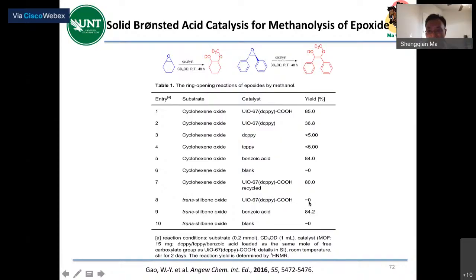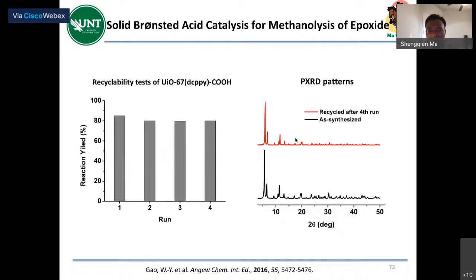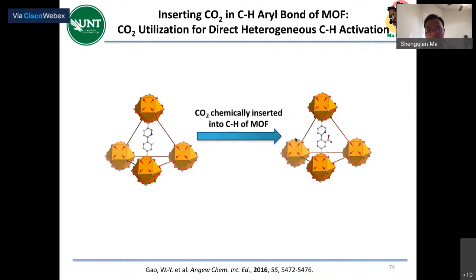There's no reaction, zero yield, because they cannot enter, because the window size of UiO is pretty small. The cavity is large, right? So we found there's no activity, but when we use the homogeneous benzoic acid, it can still catalyze this substrate. It's comparable to this smaller substrate. That's a strong indication that the carboxylate formed to catalyze this reaction is from CO2 insertion, and is also within the inner pore of the MOF. Of course, the catalyst can be recycled and is also very stable. And of course, this is the very first demonstration of direct CO2 utilization for this heterogeneous C-H activation in the MOF.